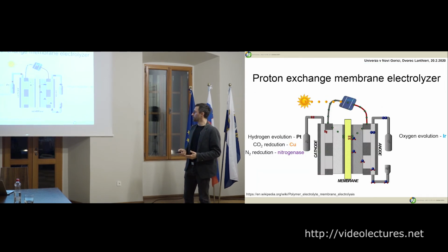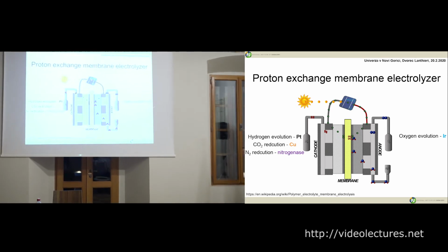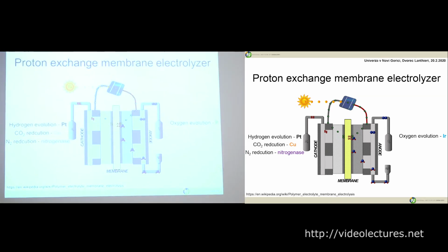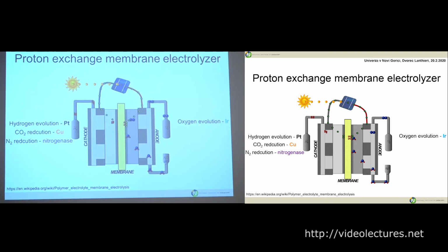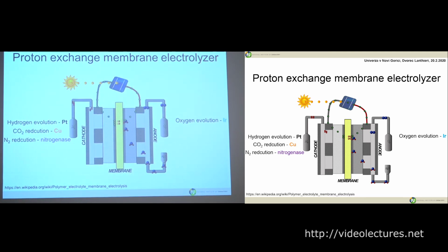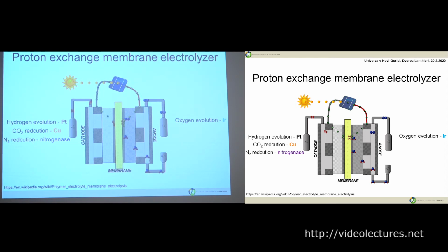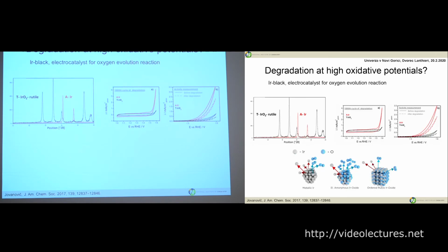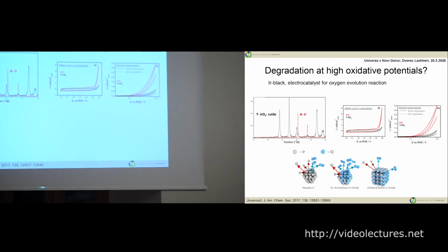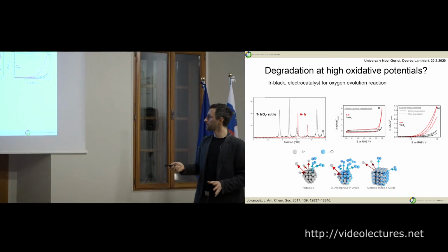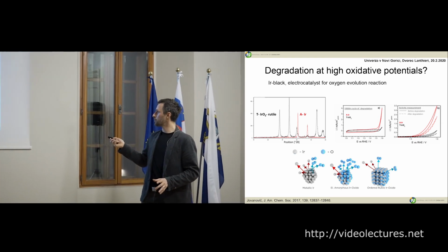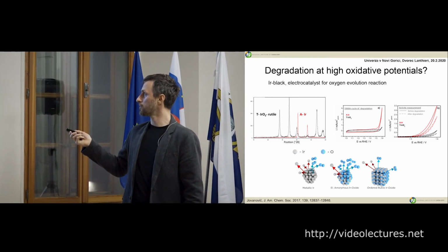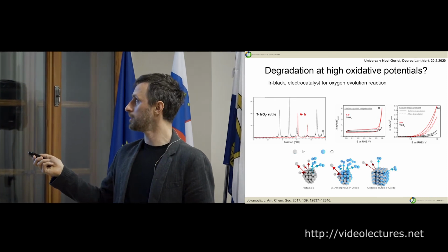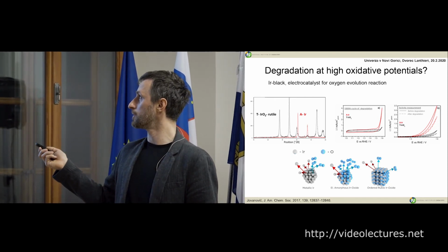So now if we go to the proton exchange membrane electrolyzer where we have iridium, iridium is the only good catalyst, and then you have on the other side these others, copper and so on. I will show faster examples here. We did a study where we compared iridium oxide, rutile oxide, and iridium metallic particles. Iridium metallic is much more active, so if you go to high potentials, you split water much better on pure iridium than iridium oxide.